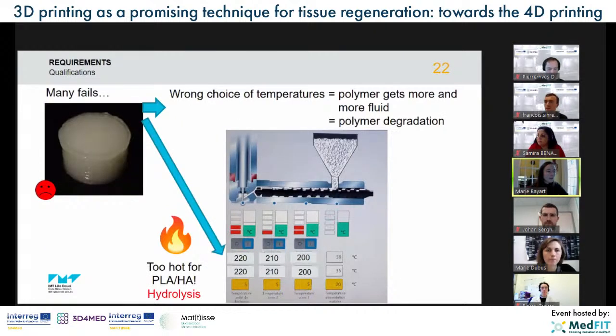In the next slide, we chose the wrong temperature. We are using PLA, which is subject to hydrolysis. And here we chose a too high temperature, and the polymer got more and more fluid because it degraded. This shows a lot of hydrolysis. So we had to choose a lower temperature.